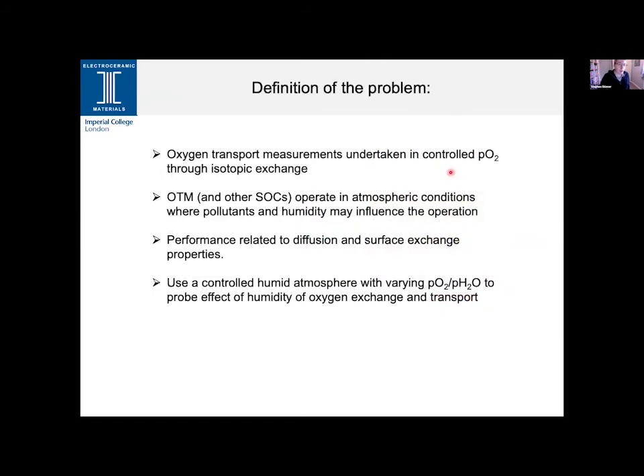So if we define the problem that we're trying to tackle, as I mentioned briefly in the first couple of slides, the transport measurements that we have typically undertaken are through well-controlled oxygen partial pressure isotopic exchange measurements under defined PO2s and typically defined dry PO2s. Now, clearly that's great for defining the kinetic parameters of your device, of your material, but those materials operate in devices under atmospheric conditions where you have significant pollutants, humidity, etc., which may, of course, influence those operating parameters.